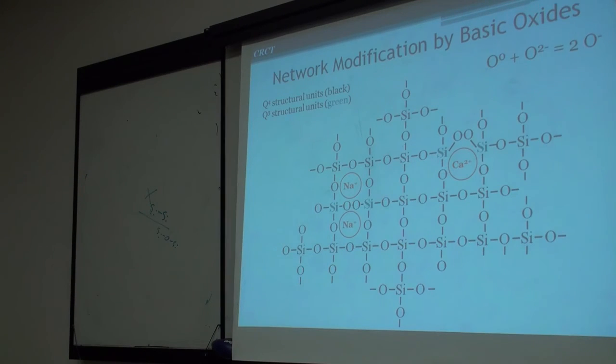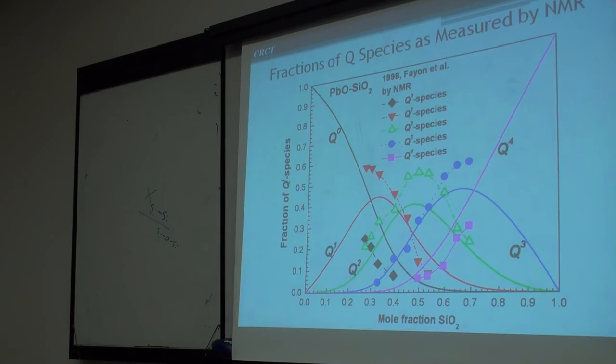And then we compare that to the NMR, and it comes out not too bad. You're not going to expect this to be right on, since the model is obviously not super sophisticated, but you can see that we're getting a not too bad representation. The Q4s come up like this, the Q3s were here. For a model based entirely on the thermodynamics, and the NMR is not all that precise either, the green ones came out kind of like that.